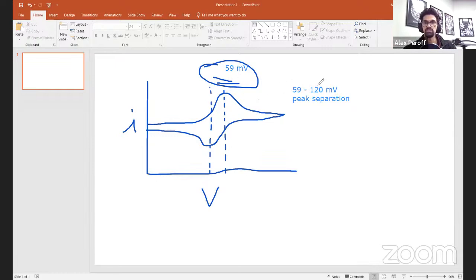The other thing, there are 2 things that, generally speaking, besides some experimental things, talk about the peak separation. One is solution resistance, solution resistance can cause it. And the second thing is the kinetics of your redox couple. Okay, so within an experimental set, these are really the 2 things. The kinetics of a redox couple are usually pretty big.